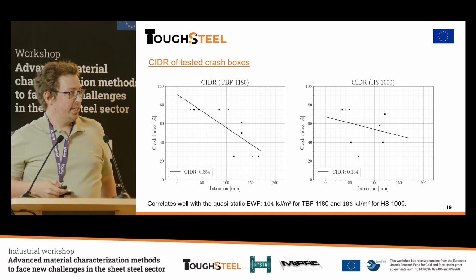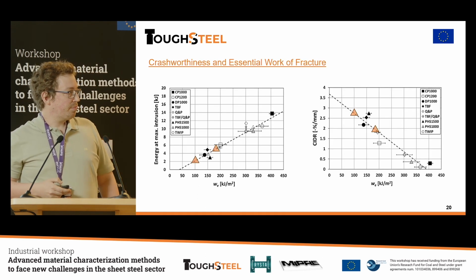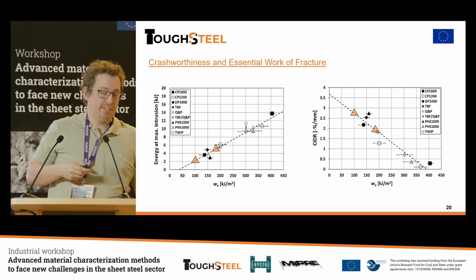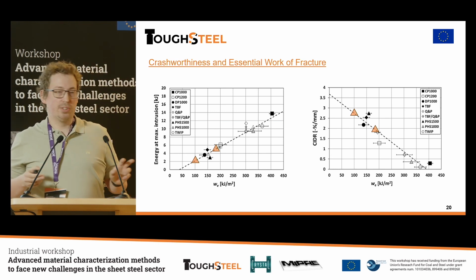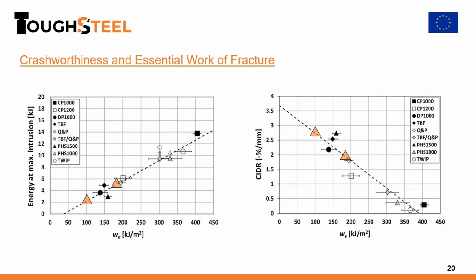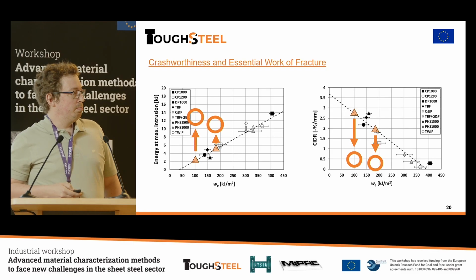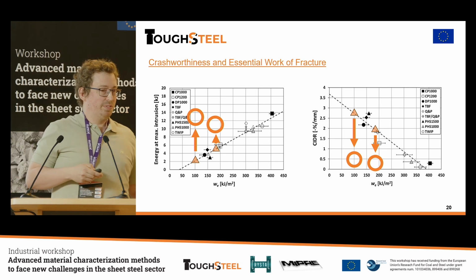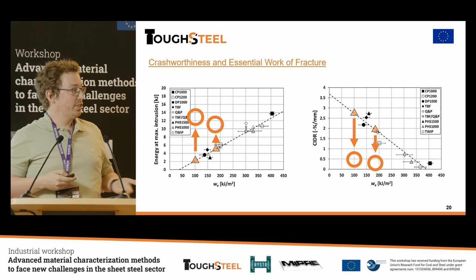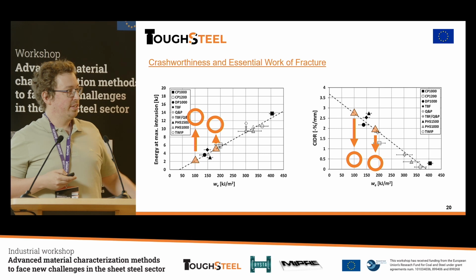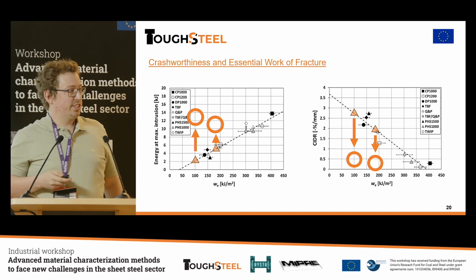And yeah, it correlates well with the essential work of fracture. So just for curiosity, I put in the published result from Frómeta here. And if we put in the essential work of fracture values here, this is what we could expect from this graph. But of course, when we received different values, a lot higher energy absorption and lower crash index decreasing rate.